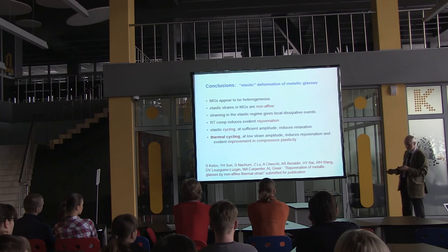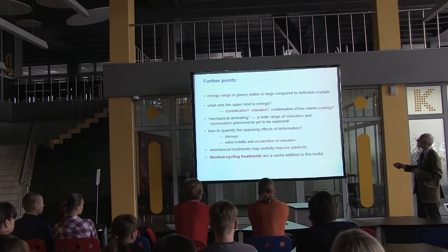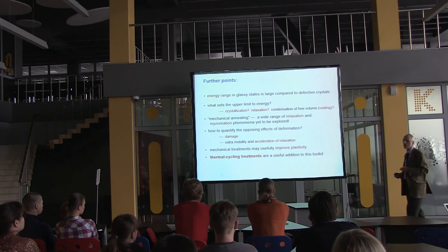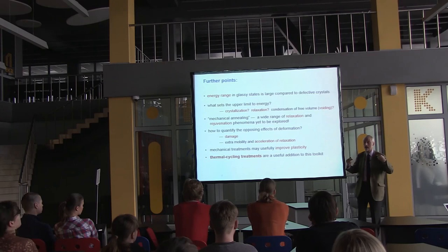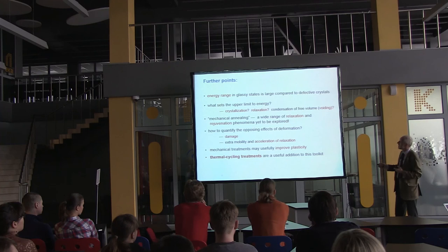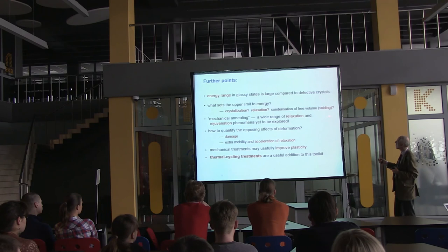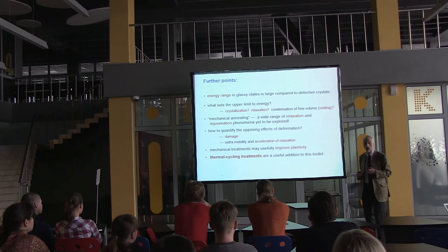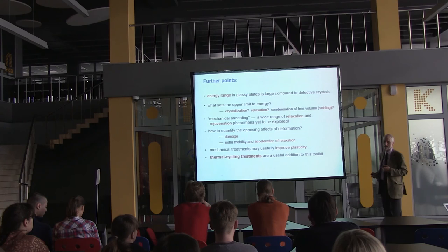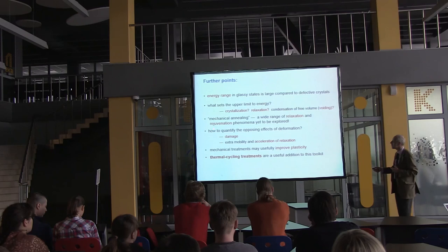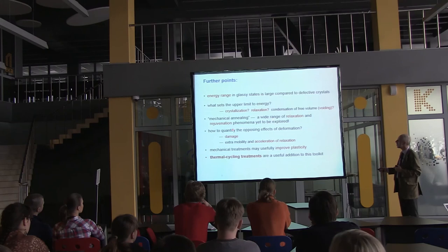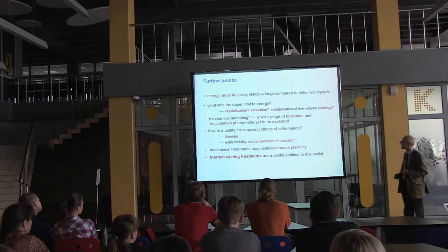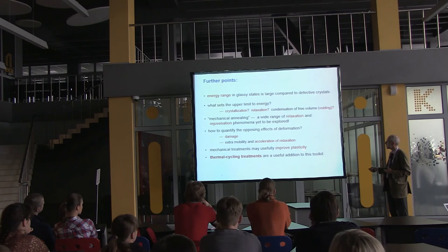The energy range in glassy states is large compared to defective crystals. Future work could ask: how high can we make the energy of the glass — what sets the limit? Crystallization, automatic relaxation, or void formation could limit it. There is also the unexpected phenomenon of mechanical annealing — familiar with annealing by heat, but also possible purely mechanically — where you do damage but also provide extra mobility, accelerating relaxation. These treatments may improve properties, and thermal cycling might be particularly useful.